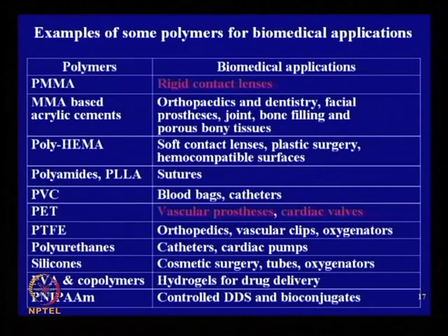PVC for blood bag. You have seen blood bag for collection of blood, that is made of PVC, although it is banned today. That is flexible PVC, plasticized PVC. It is banned globally, but in India nobody bothers. So, we are using this flexible plasticized PVC. The problem is, it gives a life to the blood for 30 days only at 4 degrees Celsius.